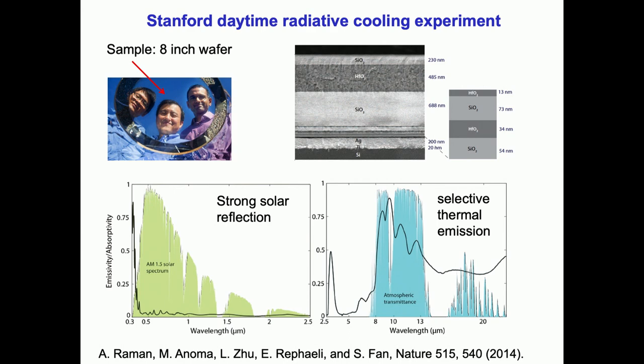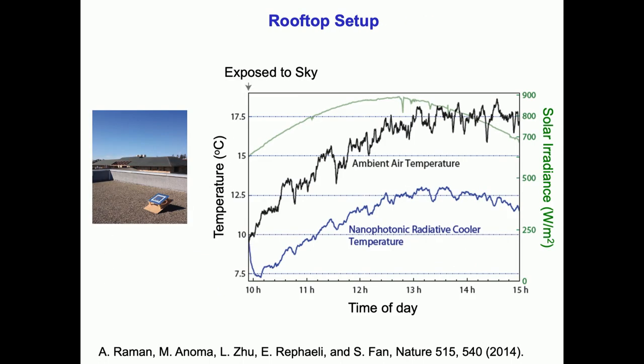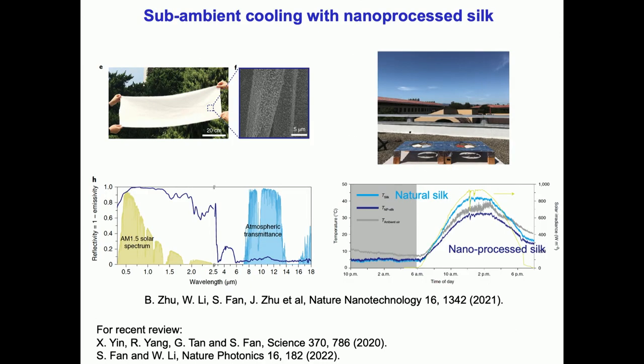And so the idea that we proposed about 10 years ago was to develop a material system that strongly reflects sunlight, but radiates very strongly in the 8 to 13 micron window. The first material that we did is a multi-layer dielectric thin film placed on top of silver. And when we put it on the roof of our electrical engineering building, we got a temperature that's about 5 degrees Celsius below ambient with 900 watts per meter squared of sunlight directly hitting the sample. Since then, there are probably hundreds of material systems that people have explored for radiative cooling purposes. And these range from, for example, textiles that I'm going to talk about, to building materials such as concrete, to wood, to a very wide range of materials.